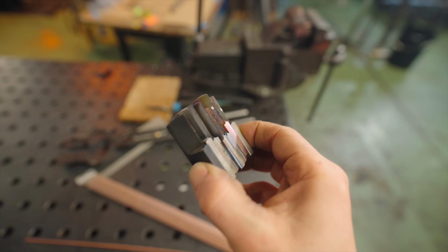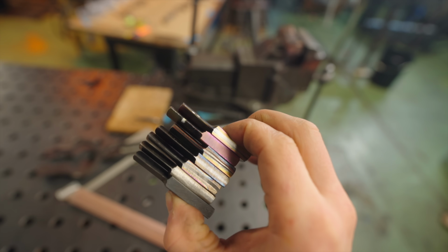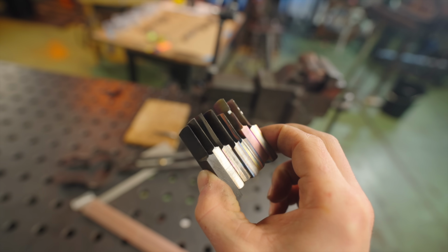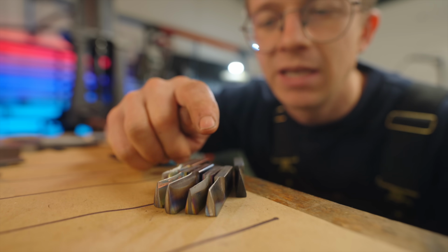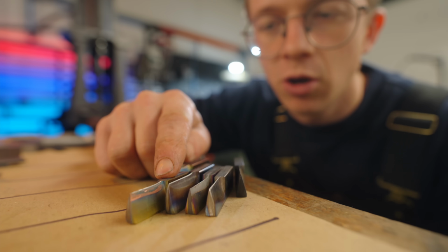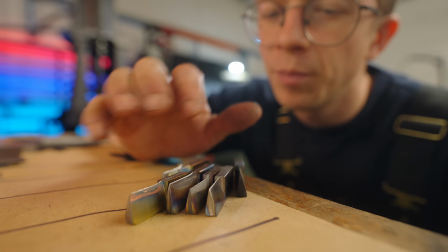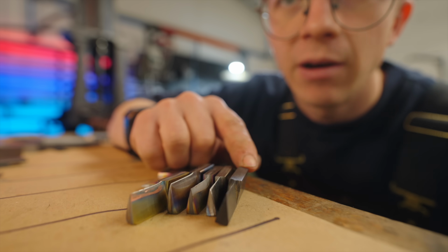It deformed. No good. I think it's about time I bought a Rockwell hardness tester, because that would be a very important metric to compare as we are planning for the best process. What did we find? The nickel interlayer samples and the copper interlayer samples. That steel core performed just as well as it did on our control.